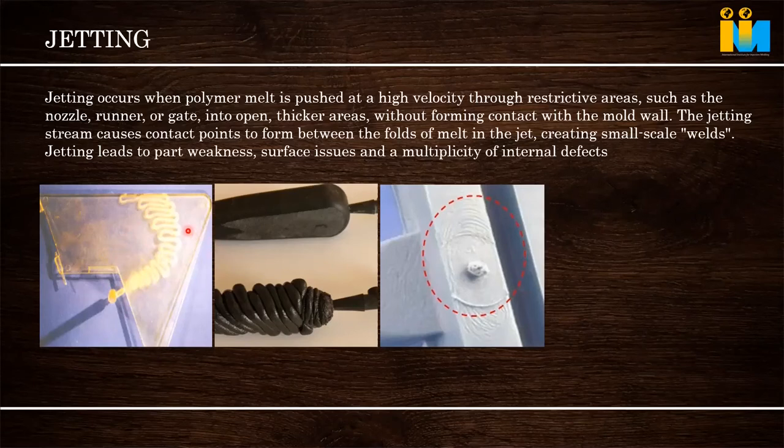So the first raw material which is initially injected cools down quickly and its color may differ from the other. That color difference, and the flow, shows as a jetting mark. This is majorly because the gate size is small, so when we inject, it suddenly shoots like anything. When it shoots at speed through the gate, due to shear the discoloration happens initially, and that shows up as a jetting mark.